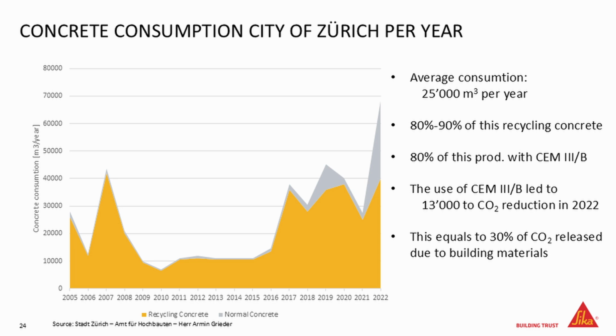When you look at the concrete consumption in the city of Zurich per year, the yellow one is the recycling concrete, and the gray one is the normal concrete. So over the years, you can see that roughly 80 to 90% of the concrete that is required by the city, and that's only for public buildings, is built with recycling concrete. You have some peaks because you need to renovate, you need to rebuild something.